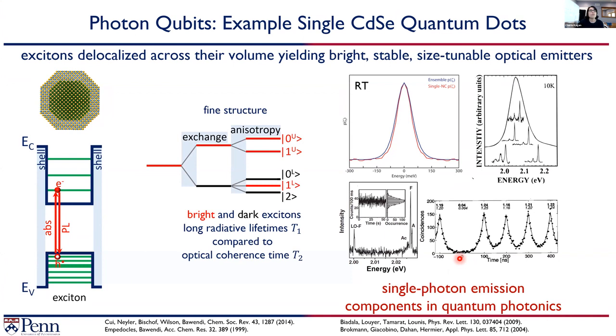Interestingly enough, and in the detail of the excitonic states, in many of the conventional II-VI, III-V, IV-VI semiconductors, and I won't go through this in too much detail, the lowest excitonic state is actually optically dark. And so as a result, as we think about their application in quantum information science, it often means that their radiative lifetimes are still long compared to their optical coherence times, which are typically much shorter, on the order of 100 picoseconds. And so this fine structure is something that is important for us to understand, and also one that can be manipulated through the design of the quantum dots. And so people have shown that you can start to tailor this, and even flip the order of some of these states by controlling their size and shape.